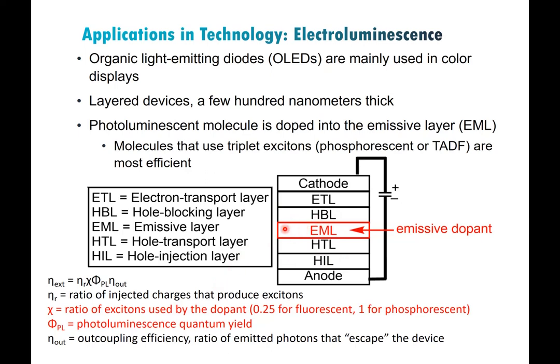And the other thing is that for phosphorescent or TADF compounds, you want the lifetime to be as short as possible. Because if the molecule is sitting in its triplet state too long, you can get triplet annihilation, and you can get what's called efficiency roll-off, where you basically populate all the excited states and they're just sort of sitting there parked in that excited state, and when you inject more charges into the device, the ones that are in the excited state haven't relaxed yet, and so you're wasting charges that way.